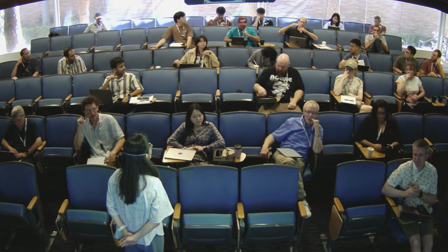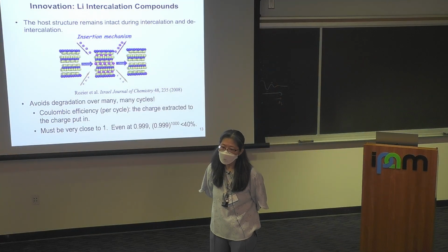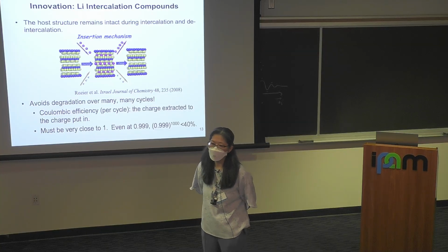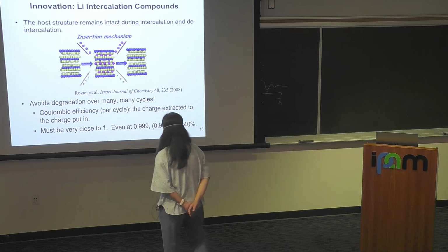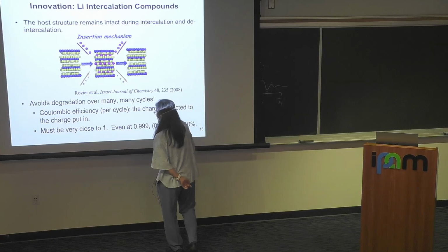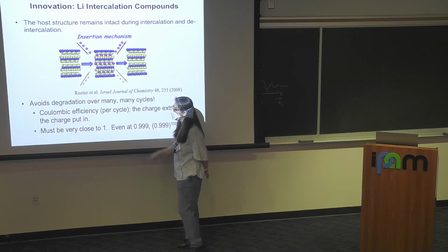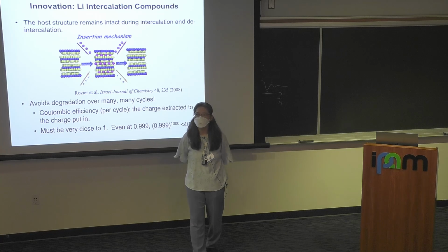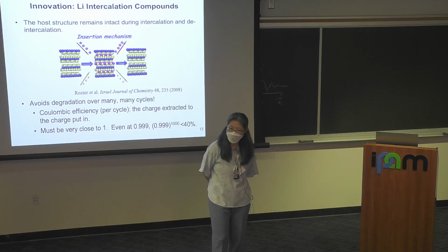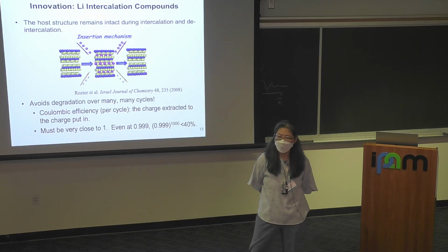Yes? But is swelling an issue? Swelling can be an issue, yes. Swelling is a big issue with solid-state batteries, especially. With liquid systems it is, but it's not as bad. Often in liquid electrolyte batteries, the poor coulombic efficiency comes from SEI side reactions, SEI formation, and things like that.